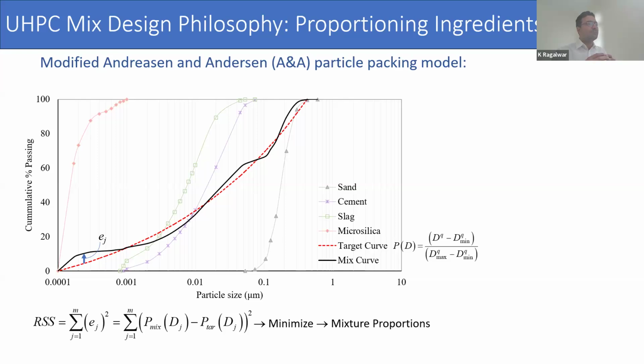when you proportion sand, cement, slag in certain proportions. So if you have sand to cement ratio as 1.5, slag to cement ratio as 0.6, or microsilica at 0.5, you take these different proportions and draw the cumulative curve. That is known as the mix curve. And then this is the target curve, which is defined by the value of Q. So the idea is, by changing the weight proportions of different ingredients, you can minimize this error EJ, and that brings you closer to your target curve.